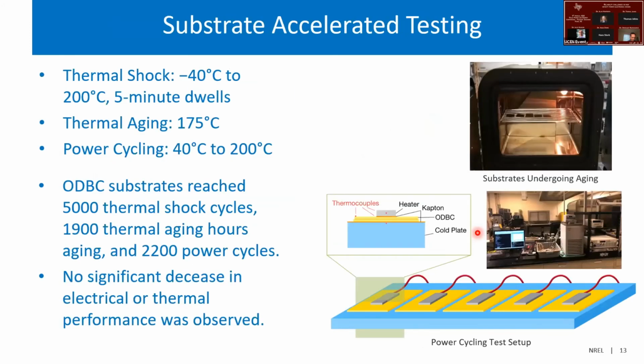We have performed experimental accelerated testing and thermal shock, thermal aging, power cycling. This is all within our setups here at NREL. So maybe some of the key conclusions are these are withstanding fairly high number of shock cycles, 5,000 shock cycles, 1,900 aging hours, thermal aging hours, and 2,200 power cyclings. No degradation in electrical or thermal performance. So it's looking promising is maybe what the key conclusion here is based on all these experimental evaluations as well.